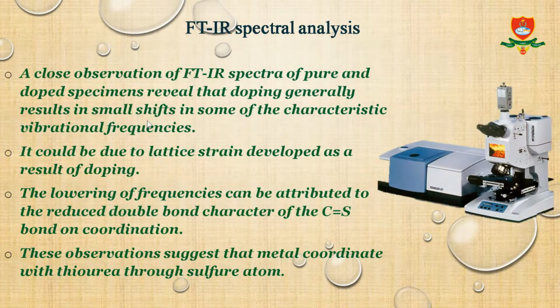FTIR spectral analysis. A close observation of the FTIR spectra of pure and doped specimens revealed that doping generally results in small shifts in some of the characteristic vibration frequencies. It could be due to lattice strain developed as a result of doping. The lowering of frequencies can be attributed to the reduced double bond character of the C=S bond and coordination. These observations suggest that the metal coordinates with thiourea through the sulfur atom.